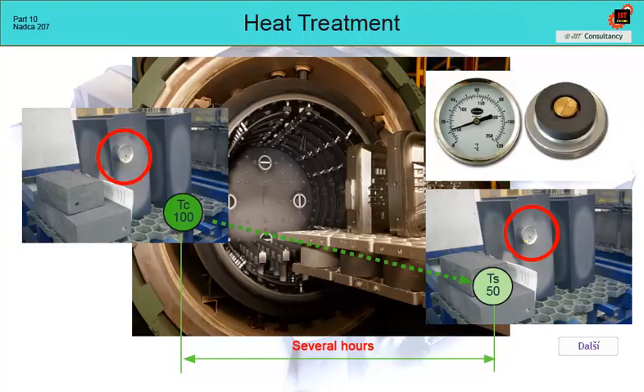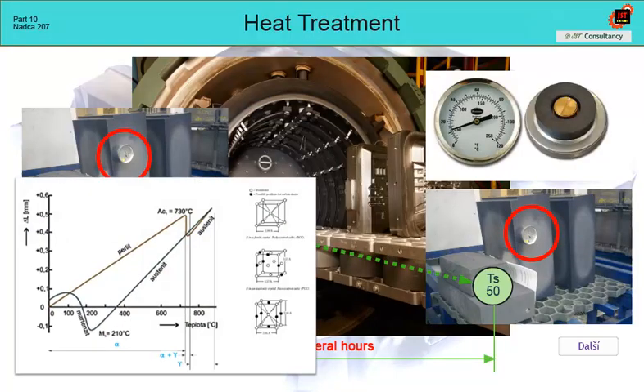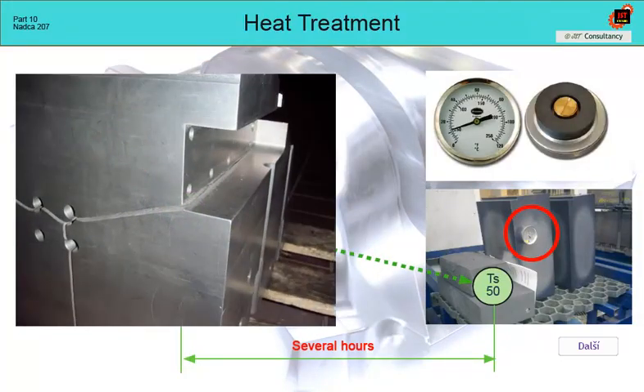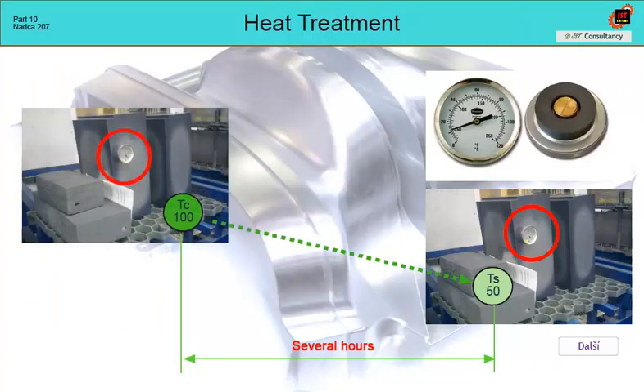This cooling period is critical in terms of internal stresses, because there is a large difference between the temperature in the core and the surface temperature, and the transformation of austenite to martensite occurs at the same time. The structure changes volume. As a result of this phenomenon, there is a superposition of stresses from the difference in temperatures and transformation stresses. And if it is in the area of tensile stresses, the strength limit of the material may be exceeded locally and the die may crack. Therefore, it is not recommended to speed up this phase of the die's cooling. This waiting period for large inserts can take several hours.